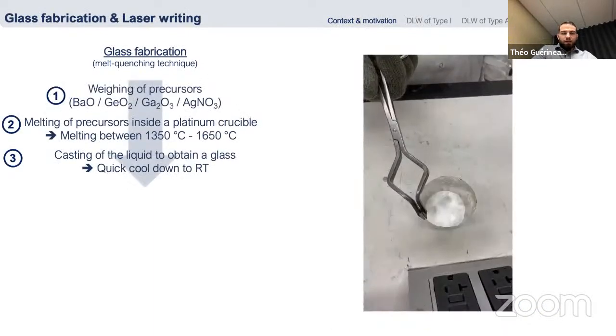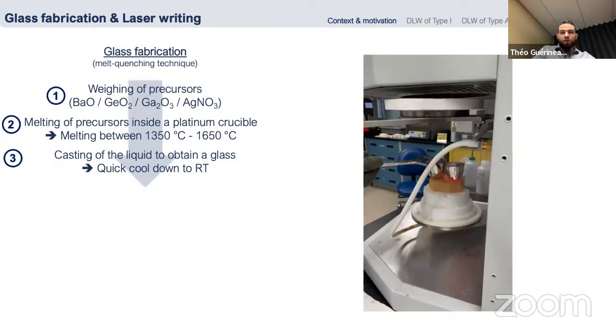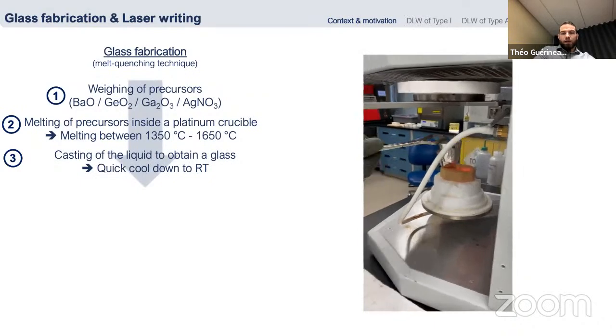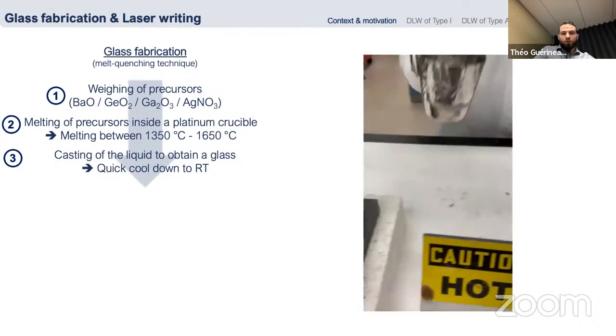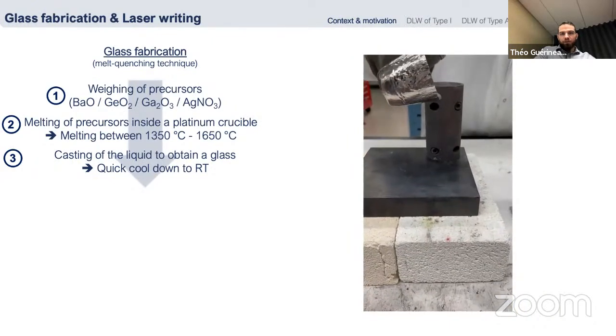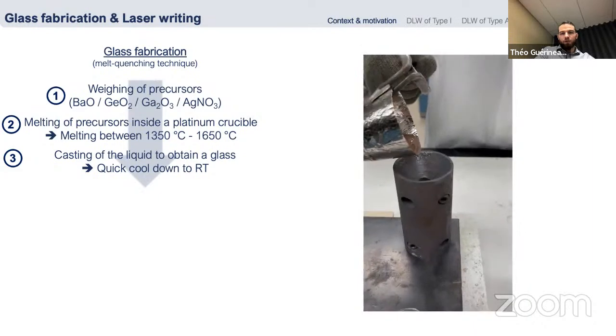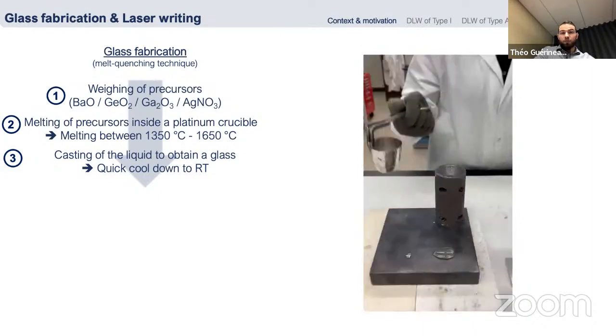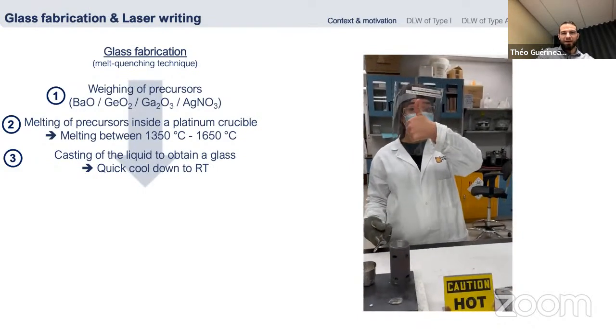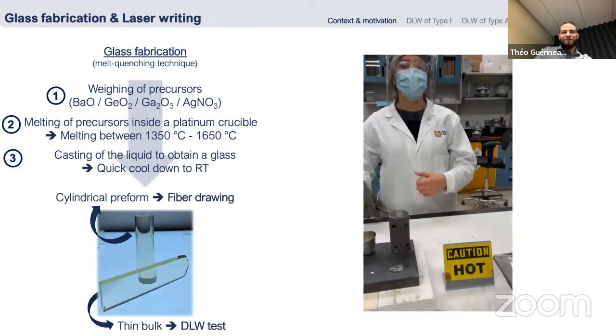So how do we fabricate our glasses? Through the melt-quenching technique. Here is just a quick video. We weigh our precursors that we introduce in a platinum crucible. We melt them at high temperature. Here we have already pre-melted the precursors. And as you can see, we can cast the liquid very easily on a metallic plate, but also on a metallic mold. At the end, we can fabricate some cylindrical preforms to perform the fiber drawing tests, but also some thin parallelepipedic bulks, allowing us to perform the direct laser writing tests.